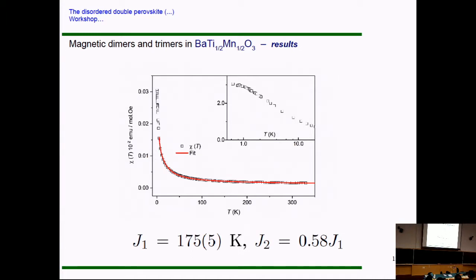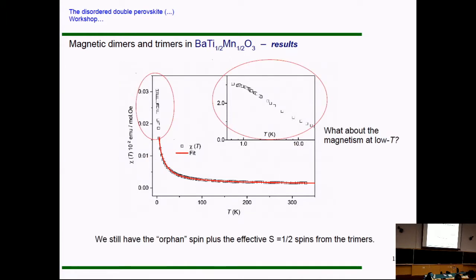just up to this point, not down to low Kelvin, because we now know that if you measure the susceptibility, let's say, down to 0.4 K, you start seeing the sign that this is no longer a simple paramagnet, but you can see some sort of sign of correlation here. And by correlation, I mean that the susceptibility is flattening as you go down in temperature. So it poses the question, what will happen to the system at even lower temperature, right?